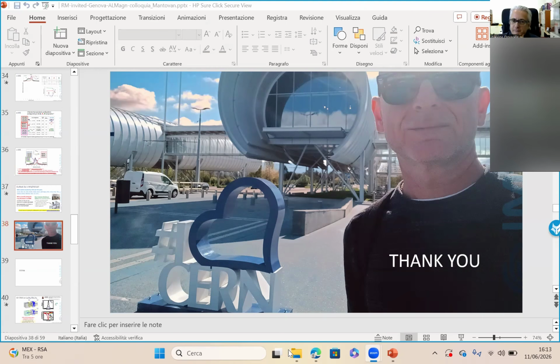Very appropriate question, and thanks for saying that. Of course, in these 10 years of work around zinc oxide, we discovered that it was a slowly relaxing paramagnetic center, it was 3+. If you have 3+, you can have this slow relaxation. If you have 2+, you don't, because you change the symmetry from spheric to more complicated, so it doesn't have this property. That's why we were implanting I don't know how many crystals, looking for any trace of iron 2+ giving a signature of magnetic ordering. That was our last trial, and we never saw it. Because if you see a 2+ that broadens and changes by applying the magnetic field, then you can, as you very nicely say, claim that there could be a possibility for long-range interaction, but unfortunately, we didn't see it. Very nice question.